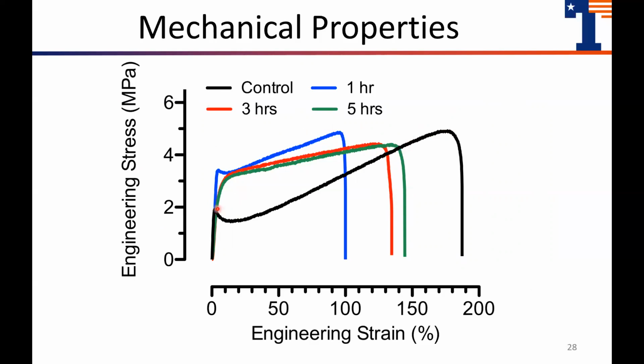One of the most important things you can see in this graph is this necking behavior that is occurring in the control. Basically, in this beginning region, the amorphous structure that is between the semi-crystalline structure is unfolding. And then once it's all unfolded, there is a sudden drop, because this is when the semi-crystalline structure starts to be unfolded throughout the experiment.